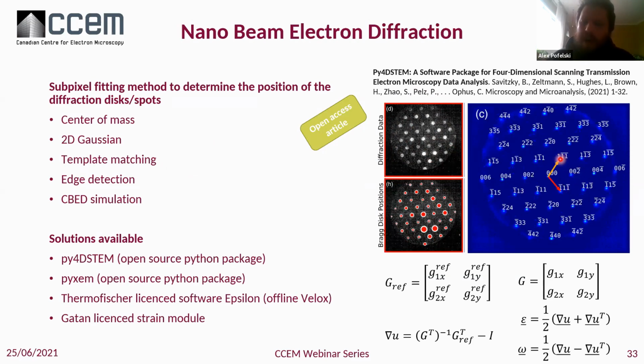And then, in a similar manner to what we were doing in the high resolution case, you will define the geometry here. So these are the two arrows, an initial geometry, and you will see this change of geometry on all the different diffraction patterns acquired on the map. And you will see exactly the same approach. You will use the G reference that you will, for example, take from one selected diffraction pattern. Then you measure the G or the delta G, depending on what you want to measure on those maps. And then, by using this matrix approach again, you can find the gradient of displacement, and then find the strain and the rotation tensor. So a very elegant piece of work. And it's also an open access article, and they are providing an open source package.